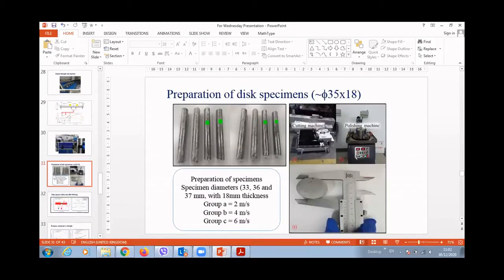To carry out this test, we need samples of about 35 millimeters diameter and 18 millimeters thickness. In our case, we have 3 different diameters: 33, 36, and 37 millimeters. In each group, we use a different impact speed: 2, 4, and 6 meters per second. The samples were cut, polished, and measured.